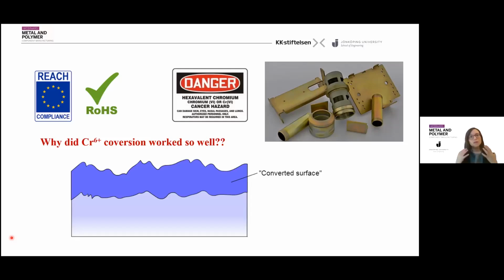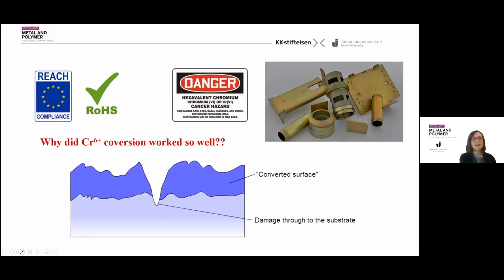In order to understand which alternatives you should use that are chromium-6 free, we should first understand why chromium-6 worked so well. So if this is the conversion coating, that is chromium oxide and aluminum oxide mixed together, and this is the aluminum substrate, we have a passivation and conversion layer. What happens when we have a chromate layer is that by any mechanical damage on the surface, the substrate would be exposed, having a hole in the protection system.